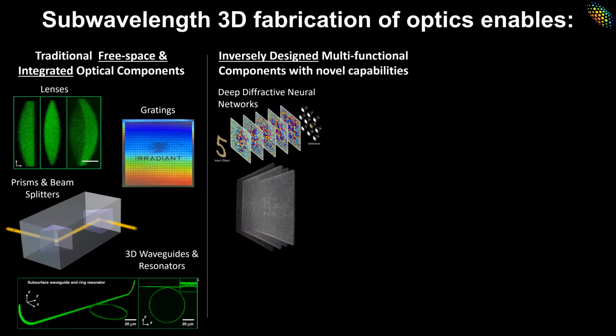So for example, so-called deep diffractive neural networks, which are essentially a series of phase plates that are precisely made with wavelength resolution and precisely aligned, and essentially take an input optical image. You can think of that like a complex valued matrix where you have a phase and an amplitude at every point in space. And then at each phase plane, that's like an element-wise operation on that matrix. And then you get free space propagation, which is roughly equivalent to a Fourier transform. And then by cascading many of these together, you can essentially do arbitrary linear matrix operations on this input image. So these have been used for things ranging from basic image identification to multispectral imaging, phase imaging, and a bunch of other things.